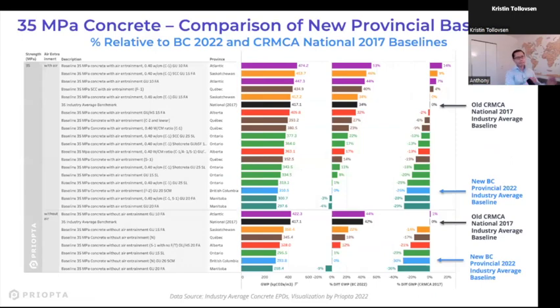So what's interesting is that last year, there are new provincial industry average concrete mixes available for all the provinces. What I'm showing here is a graph of 35 MPa concrete with air entrainment and without air entrainment. The different colors represent the different provinces, but the black one is the old industry average, which was from 2017. At the time, we only had a Canadian industry average. We didn't have provincially specific industry averages. But now, as of last year, we do.